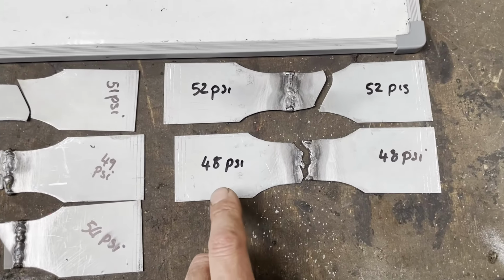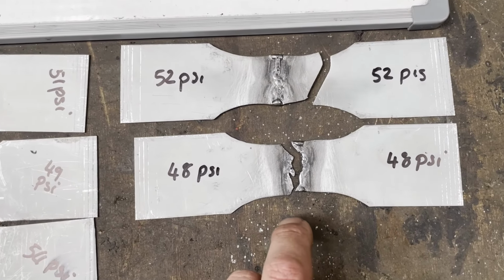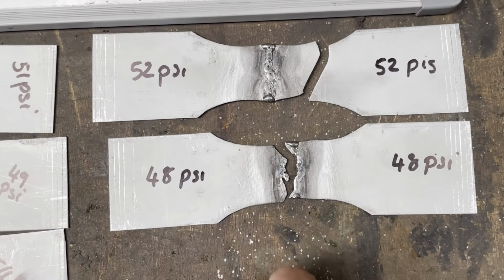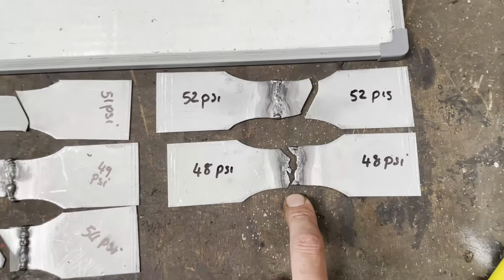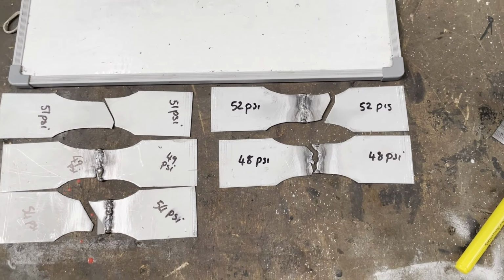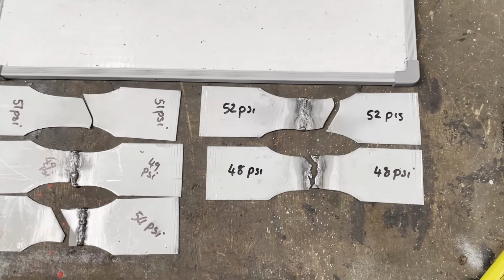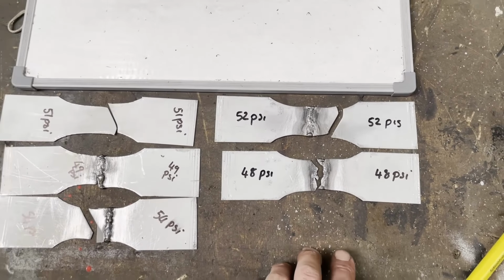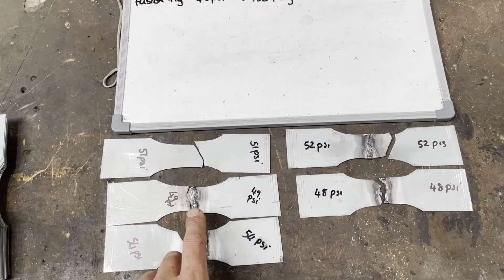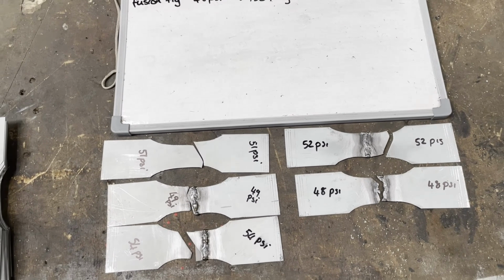Fusion TIG then, 48 psi, nothing wrong with that. It broke right along the weld, so I'd say this is the weakest weld of the lot so far, which is not surprising because you're going to get some undercutting where it fuses together. Let's try a MIG butt weld that's been ground down.